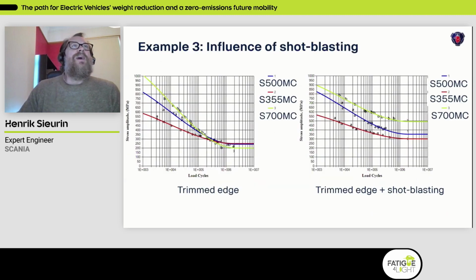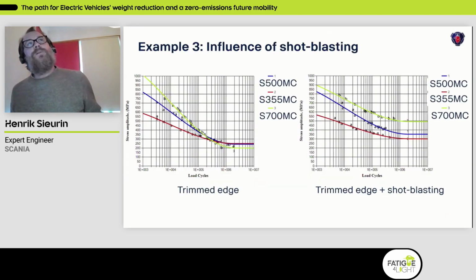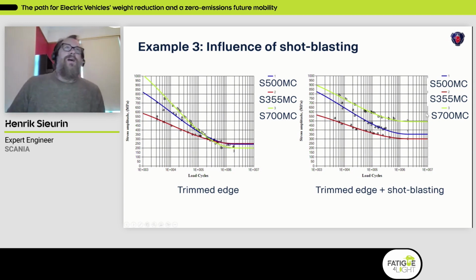And then I continue with another example of how to increase the fatigue strength in a chassis component, and that is by this mechanical surface treatment. These 2 pictures show the influence of a simple shot blasting. Shot blasting is mainly done to increase the corrosion protection, to improve the painting, to get rid of oxides, scales, and so on. But as you see, it also has a really positive influence on the fatigue strength.